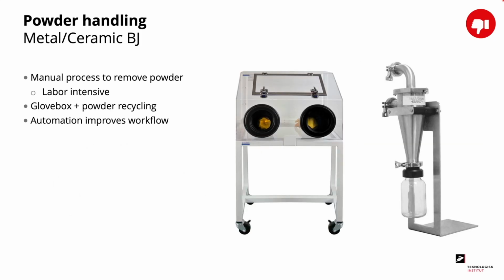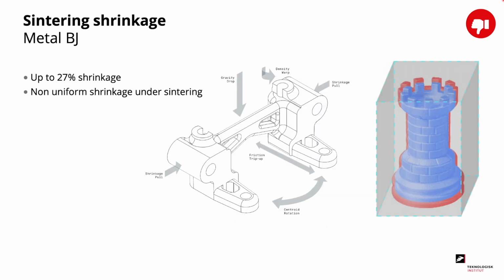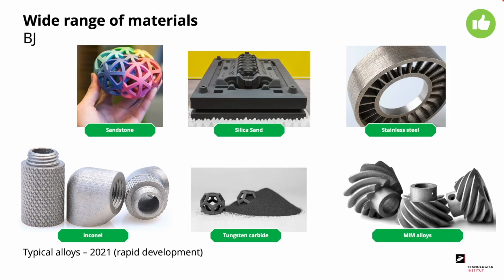Another downside of binder jetting in metal and ceramics is the powder handling. This is a labor-intensive manual process to remove the powder, and you need a glove box and a powder recycling station. It would be possible to improve this workflow through automation. Another downside of metal binder jetting is the sintering shrinkage. You get up to 27% shrinkage for some materials, and this shrinkage may not be uniform because you have friction and you have gravity.